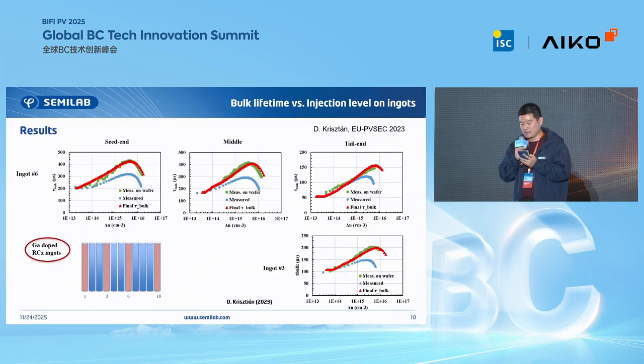However, we did it, and we first applied this unique iterative evaluation technique on different P-type ingots from an RCZ pulling sequence. The results indicate convincing agreement with values obtained on neighboring wafers with symmetric amorphous silicon passivation.